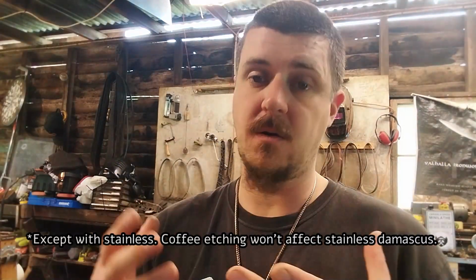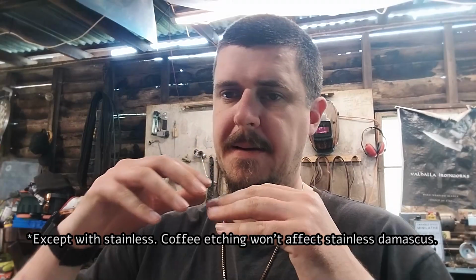But you don't worry about your blacks at this point if you want to do good Damascus etching, because the oxides left over from things like ferric chloride and hydrochloric are not particularly stable. They're all right, don't get me wrong, they'll hold up okay, but if you want that piece to really last, that's where coffee comes in, because coffee produces tannic oxides. So where the acids like ferric chloride will leave oxide layers sitting on top of the steel, the tannic acid in particularly shitty coffee actually bonds with the steel and creates a layer that's interwoven with the surface of the steel, creating a much, much stronger bond and less likely to break off and wear away over time.